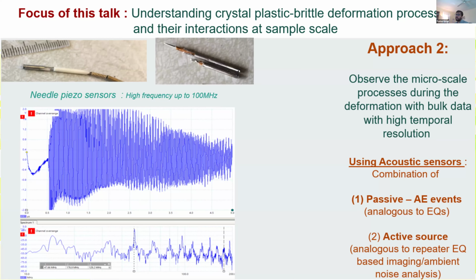One is that we can have AE events. So as you're deforming the rock, you produce small microfractures or twins. We have acoustic sensors that are touching the sample on the outside. And as a consequence, you can listen to the small events. By looking at the shape of the waveforms, where they're located and so forth, we can get some information on the AE events. And they're analogous to earthquakes in the field. The other approach is to have active source, where we can send a pulse from one side of the sample and then listen with receivers at other locations. And that's analogous to either using repeating earthquakes to probe the path effects or using ambient noise tomography in the field. So there's actually some analogy. The actual frequency content and the actual setups are different between the lab and the field. So they're not exactly one-to-one, but there's a point of connection at least.